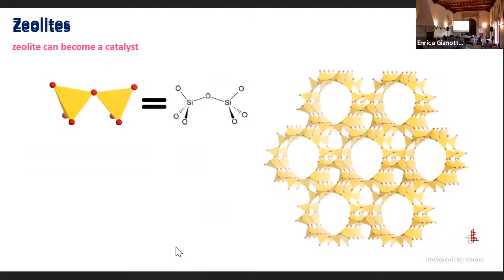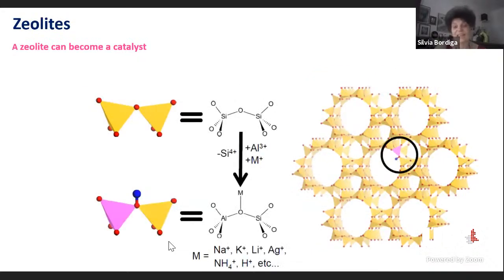I said we have the possibility to play with the framework, but also with the chemistry. And so by replacing some silicon with, for instance, aluminum, we obtain materials which have, for instance, acidity if the counter ion is the proton. And in this area, we have a large variety of applications of zeolites, for instance, in the area of petrochemistry.